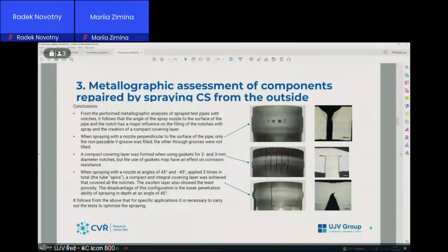We can say then if we use nozzle perpendicular to the surface of the pipe, only non-passable V-groove was filled. The other through grooves were not filled. You can see that here. When we performed spraying with gaskets for 2 and 3 millimeter diameter notches, we could see good results, but then it's a question of corrosion resistance of this. And the best results were when we were spraying with a nozzle at angles plus 45 degrees and